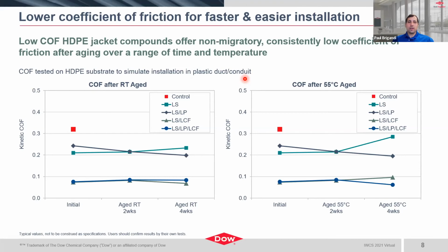Yeah, I would say in this case, what we were trying to do was more of a relative simulation of field aging. I think we settled in the middle, between a typical ambient condition and the very high, just looking to get a relative sense of whether there was any migration or any impact on COF. We didn't really get into the upper extremes on the plaque testing anyway, but it's certainly something we can consider. Yeah, I think it's related to what's normally performed. And we were just looking more at performance as might be related to reels sitting around over time. Reality, basically. Yeah. Very good.